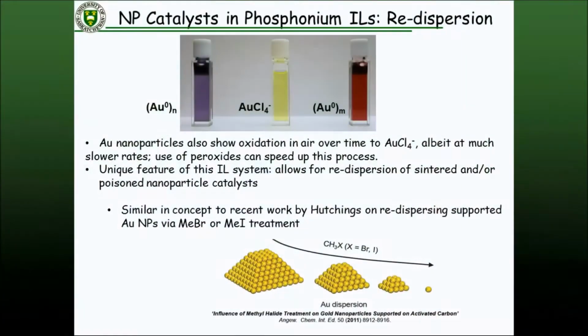So this is a particular picture of particles which we sintered, a much larger particle size, closer to 10 nanometers. We've re-oxidized them, we add the reducing agent, and we're down to a system that now has a particle size of about 3 nanometers. I like the gold because the gold has the nice plasmonic color that changes with size, so you can visually see what's going on just by the UV-vis alone. This is really all interesting.